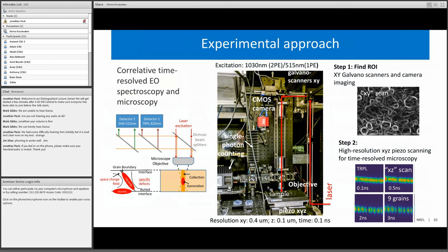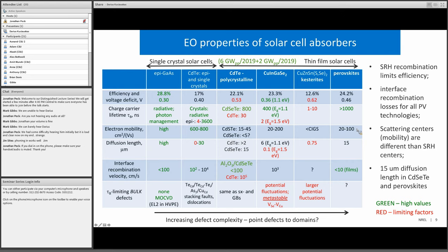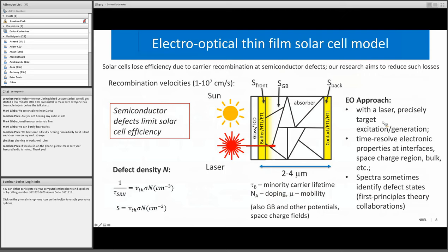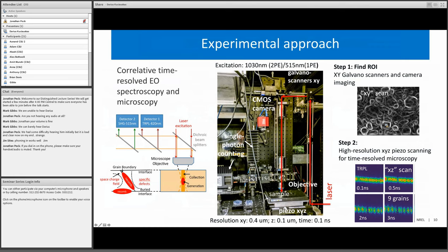the experiment that we do. In a sense, we have a laser, we shine the light on a sample, we raster the beam over the sample, we record the image with this red camera, and we see the white field, several hundred micron large field image of the grain boundaries in the material. Once we identify an interesting region in this film, then we do slower but time resolved microscopy measurements. For example, the illustration on the bottom right shows time-dependent luminescence as it changes from 0.1 nanosecond to 3 nanoseconds, and these dark regions are the increased grain boundary recombination.